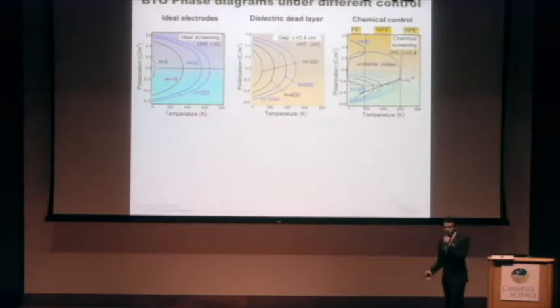So this is what we call the mixed electrochemical ferroelectric state, or the so-called ferroionic state. The reason we call it this is because in this case, the stability of the ferroelectric phase is more or less determined by the surface ionic species that are present. So depending on this value of delta G, you're going to get slightly different polarizations. And that's in fact what you would expect if you have a mixed electrochemical boundary condition.